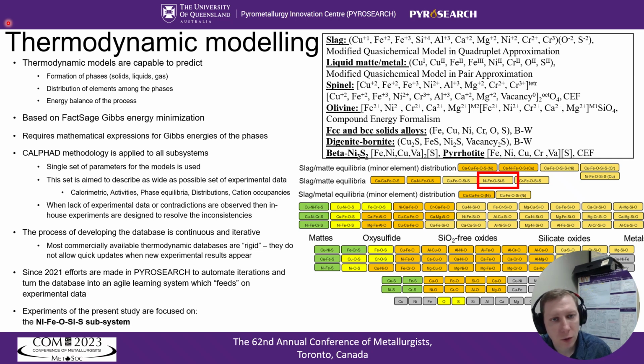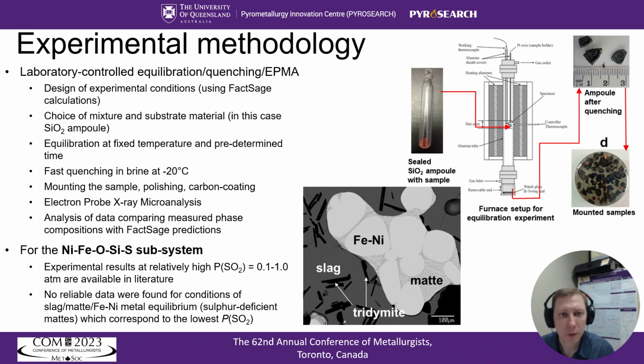Today we will show a small part of the experimental data generation step, which will be used in the development of the database. Let's have a look at the experimental methodology using an example of the nickel-iron-oxygen-silicon-sulfur system. The method of choice in our lab is the equilibration, quenching, electron-probe microanalysis technique.